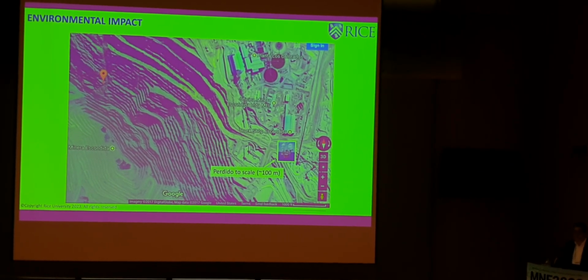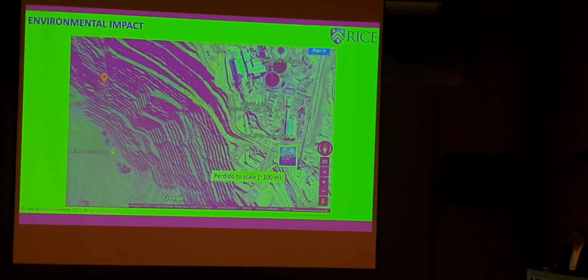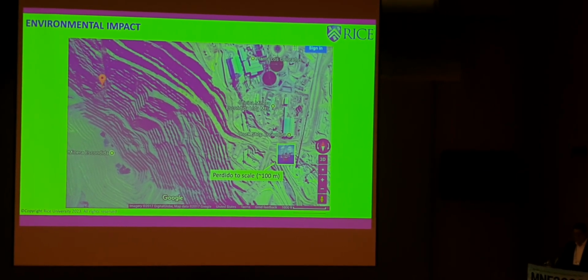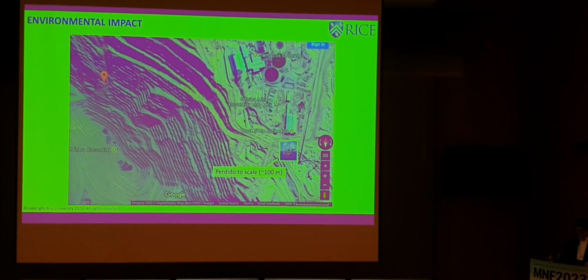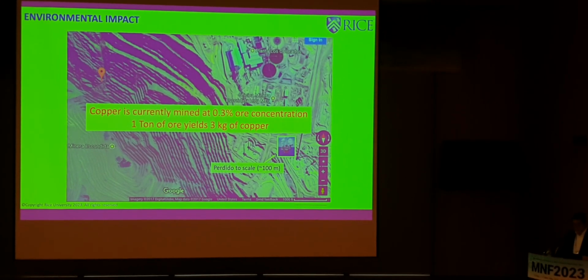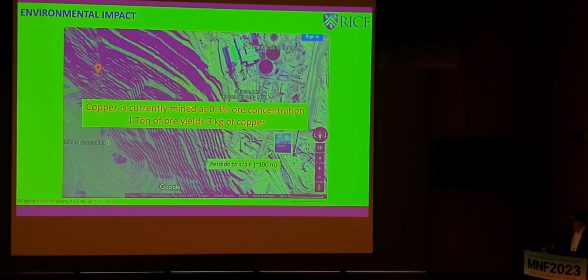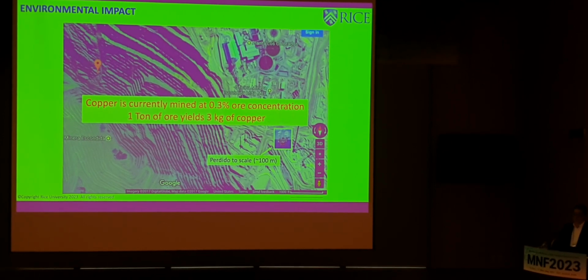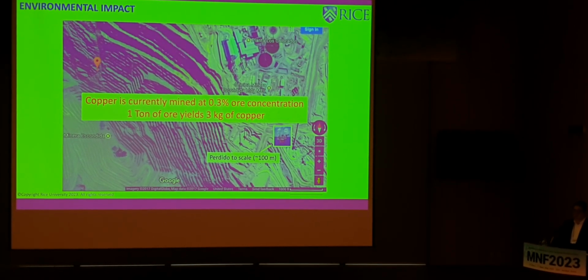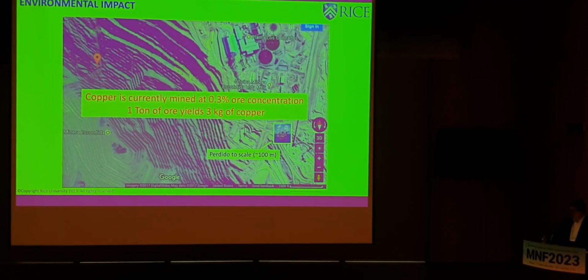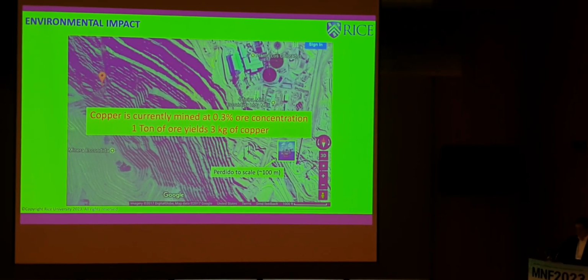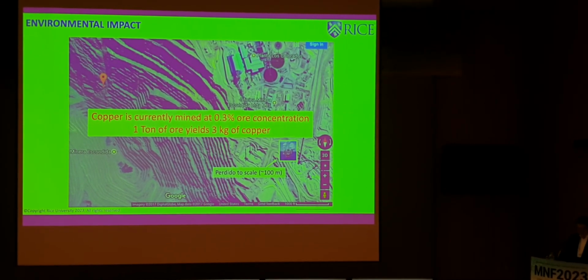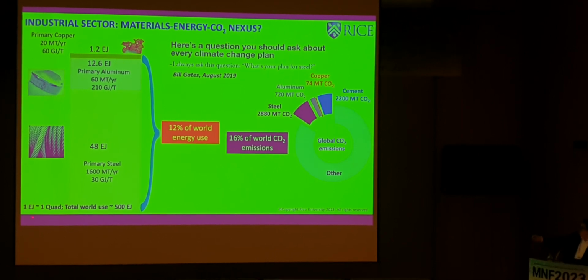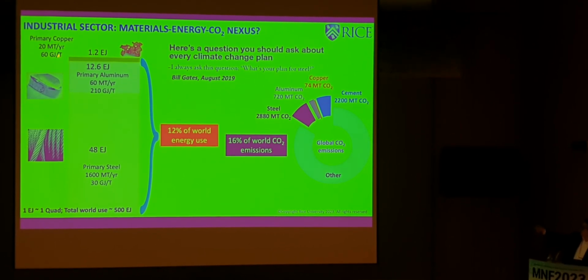So in terms of an extractive industry, oil and gas has a very, very low footprint if you do it properly. And the reason is copper, for example, is currently mined at 0.3% concentration. So you need to move a ton of rock to get 3 kilos of copper, and these are current mines. As you look at projected mines, these numbers go down. Then if you look at the energy we use, it's about 12% of the energy used.